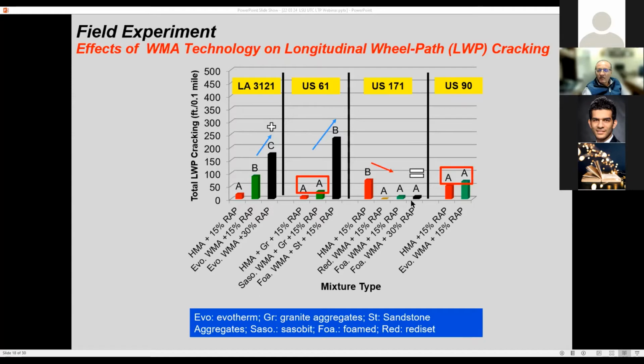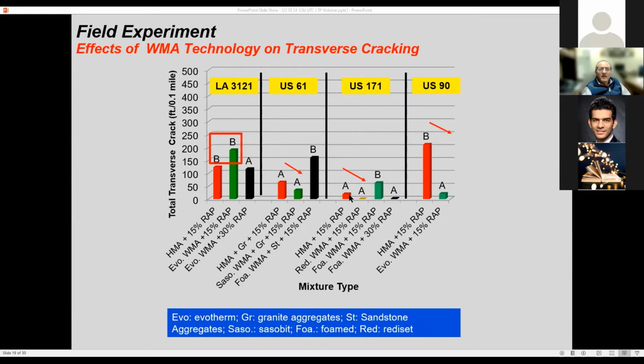Further, if you look at the effect of that 30% RAP, it does show a slight increase, however, it is statistically similar. Now, once again, you see that there are effects of the underneath layer that may cause some results that do not match what's expected.